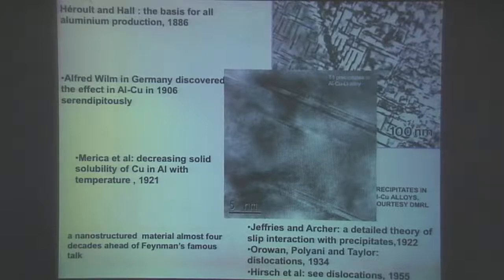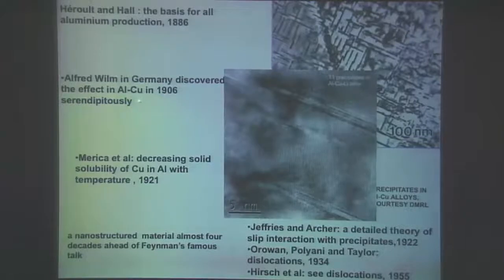There's a story here which is, I think, a very instructive story. I've heard it secondhand, so I can't vouch for the complete truth of the story. Metallurgy in the days that aluminum was being investigated was dominated by the knowledge of steel. And steel is all about quenching to form martensite and making it hard and then tempering it to get the right sort of properties. What people were trying to do in those days was to follow that background knowledge. So they quenched lots of aluminum alloys and looked at their hardness after quenching to see if you can get a hard martensite. And that was what Alfred Wilm was doing.